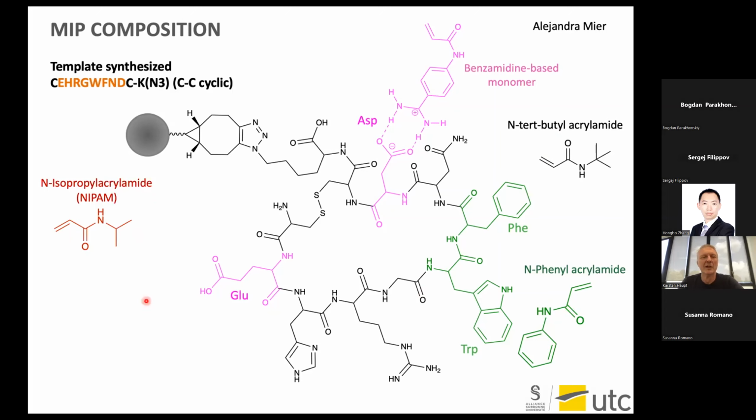And of course, you know what are the properties of polyisopropyl acrylamide or polyNIPAM. These normally can give, if used in the right proportions, thermoresponsive polymers. And this is also important for our application, as you will see. And then we need a crosslinker, methylene bisacrylamide, and the polymerization initiators, which in this case are very, very simple. It's just a redox initiation system with potassium persulfate and TEMED. So all this we need, and now we are ready to do the polymerization.